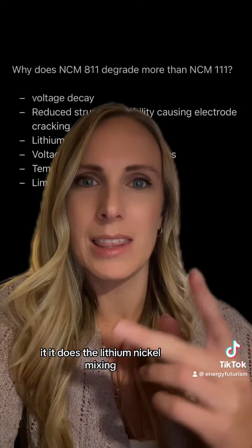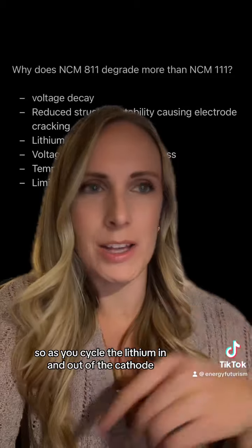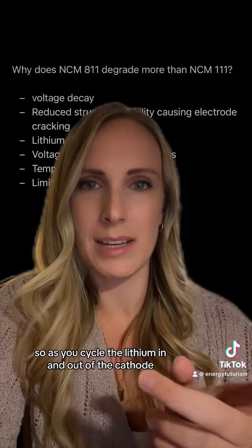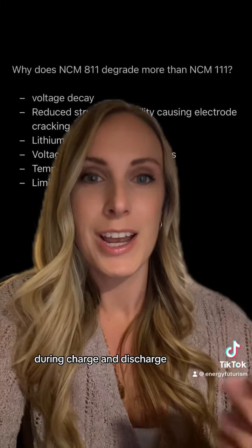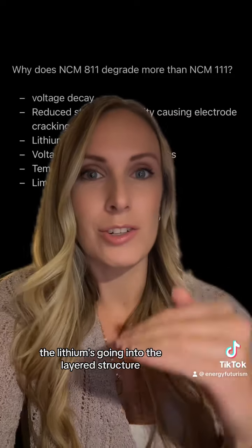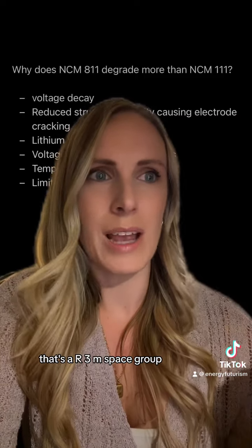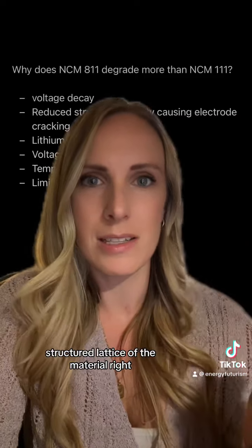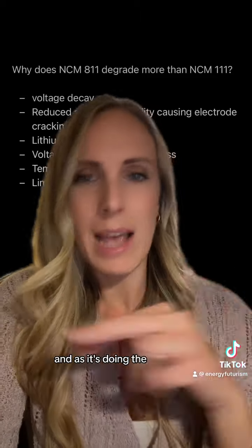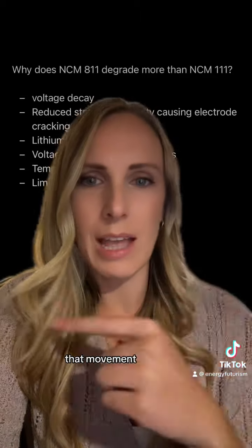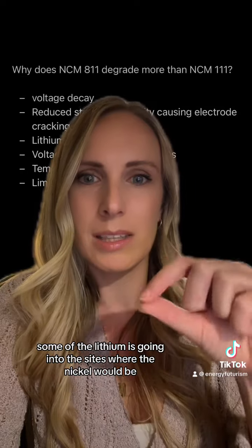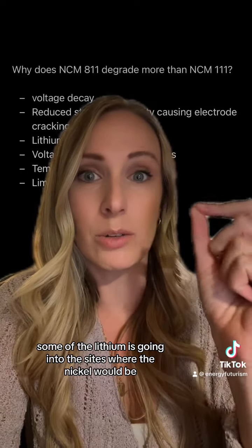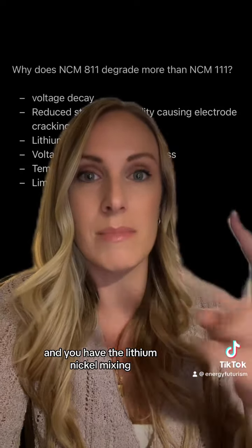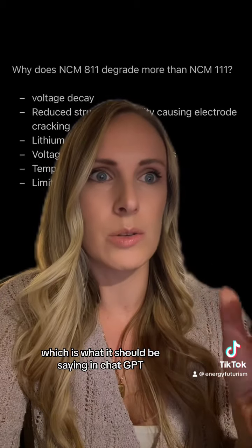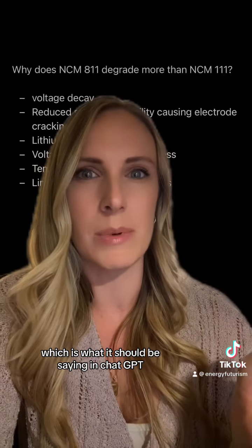It does the lithium nickel mixing. As you cycle the lithium in and out of the cathode during charge and discharge, the lithium is going into the layered structure, that's an R-3m space group lattice of the material, right? And as it's doing that movement, some of the lithium is going into the sites where the nickel would be, and you have the lithium nickel mixing, which is what it should be saying in ChatGPT, but it isn't.